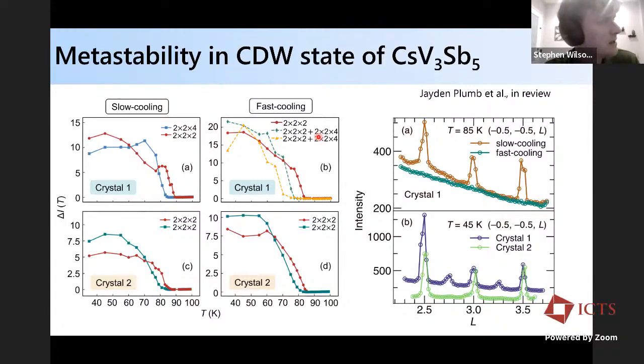but one distinction I will say is that for the cesium system at least, the in-plane charge order pattern seems to be different from a couple of different probes, meaning you seem to have a mixture of both Star of David and inverse Star of David layers. That's seen via average structure analysis from X-ray, as well as angle-resolved photoemission, which claims to see band folding consistent with that. So that seems to be another distinction, perhaps.